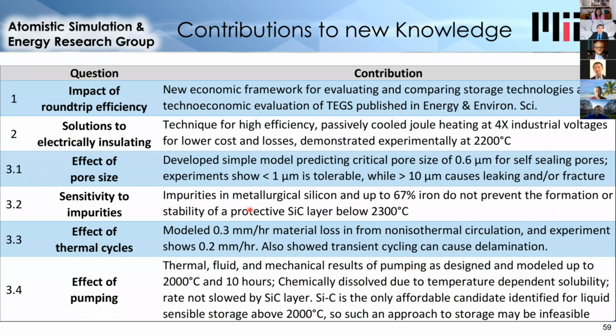But these conditions are only true if the system is isothermal. And so when investigating the effect of thermal cycling, I showed that under non-isothermal circulation, there's drastic material loss, whether the silicon is pure, whether iron's present, just because of the solubility of carbon and silicon. And so this is the key problem with this technology: when you pump between a hot and cold area, the graphite containment dissolves.